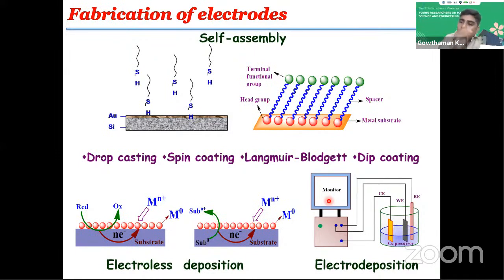If you want to attach the gold nanoparticles on a glassy carbon electrode, then you can use the Au-N bond, that is, the amine linker. So likewise, we have different approaches for linkers: the thiol linker and the amine linker. We can also use drop casting, spin coating, and dip coating techniques. Then electroless deposition and electrodeposition, two kinds of deposition techniques.